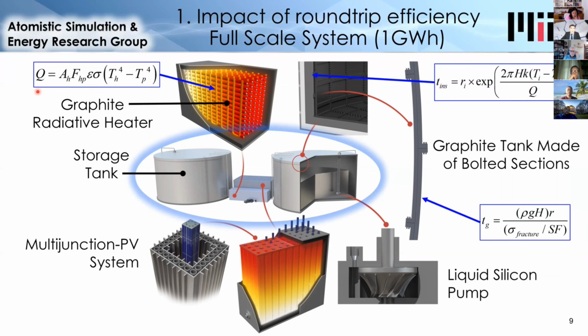And the heater is actually the hottest component in the system, hotter than 2400 Celsius, because it needs to be able to transfer heat. And so this equation is just radiative heat exchange. And what it showed is that the heating element needed to be about 2500 degrees Celsius in order to heat the silicon to 2400 degrees Celsius.